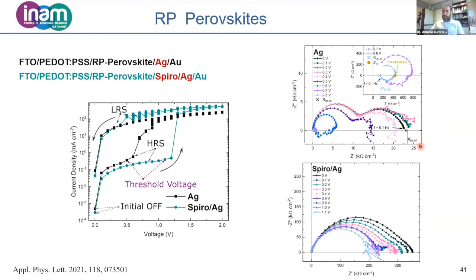And here, as you can see, the response is totally different. When we have the reactive interface perovskite-silver, this is the top graph here, we see the appearance of this hook. I mentioned previously that this was related to the chemical reactivity of ions with the contacts. We get this signal very reproducibly, and we know that it's not an artifact. And when we place a spiro layer between the perovskite and the silver, now we see the absorptive response. First of all, we see the high frequency arc: this spiro is not doped, so it's highly resistive, so the high frequency arc is related to the spiro itself. And now we don't see the appearance of the hook, because what we observe is the absorption of ions going through the spiro layer, and this is why the system is working as a memory store.